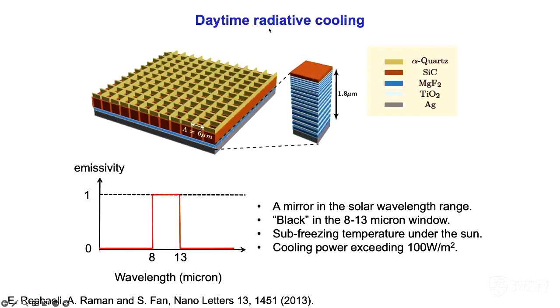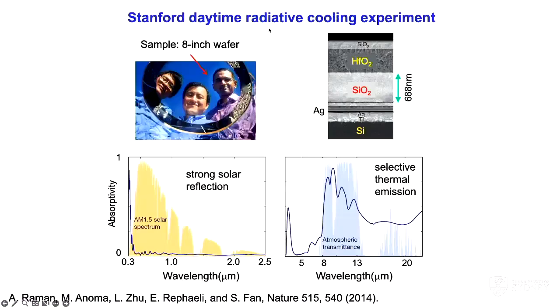Of course, when we published a theory like this, it looked like yet another strange-looking theoretical prediction. But we took our theory fairly seriously, and we spent quite a bit of time thinking about whether we could simplify this design to give us an experimental demonstration. So we eventually constructed a structure on an 8-inch silicon wafer. The picture on the left shows Aaswath Raman, who is now a professor at the University of California in Los Angeles, and Linxiao Zhu, who is now a professor at Penn State University.